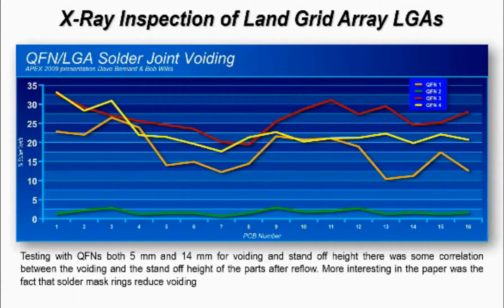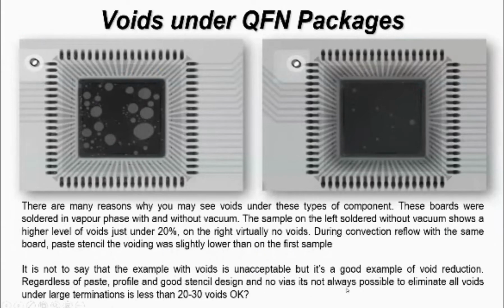And just to back up, this is going back to 2009, a paper that I did. Well, David Bernard did the paper. I just sort of was there, where we looked at the performance difference between using solder mask around vias and not around vias. And the green line right at the bottom is the lowest percentage of voids in the solder joint, which sort of backed up what I believed and I've demonstrated in the past. So there is a value in that particular area.